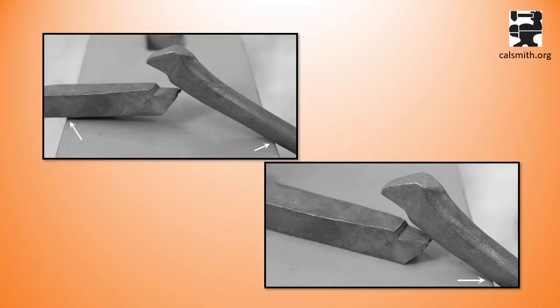So let's look at what's happening on the anvil. To position these pieces so that they match up where you want them to, you're going to need to steady them on the side of the anvil first. Drop the tong-held piece flat onto the anvil first, step up, and then with the other piece still anchored on the side, maneuver it or position it into place so that these indices match up nicely. Then you can drop your tongs and pick up your hammer.